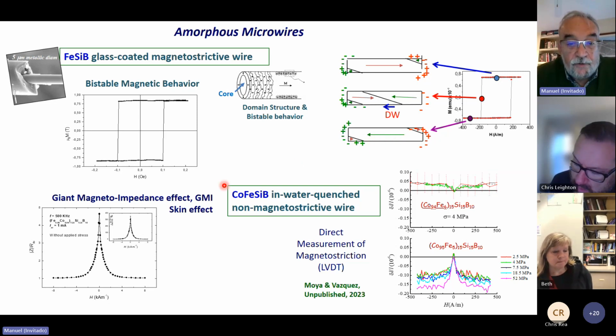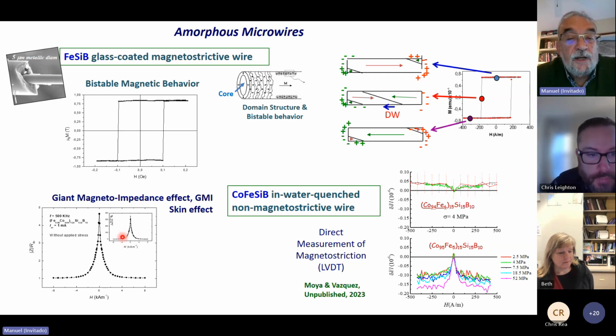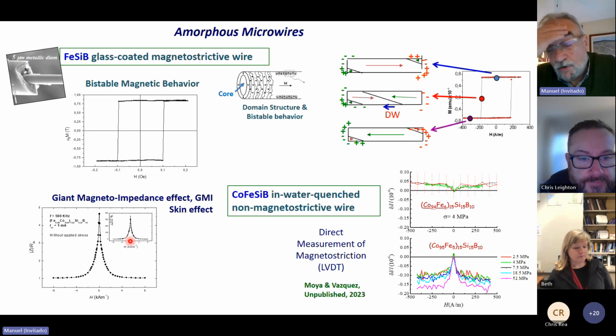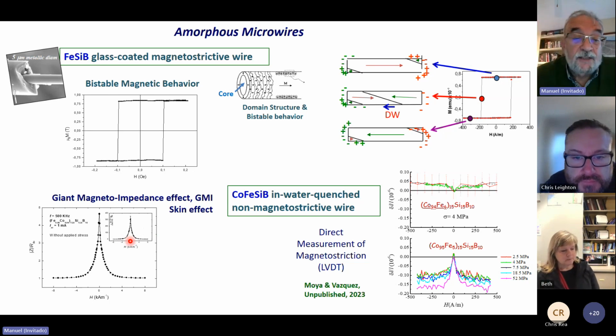In the case of cobalt iron based microwires, they are not magnetostrictive, and they are characterized by the giant magnetoimpedance effect, which is a classical effect based on the skin effect, by which the impedance of the amorphous wire drops very drastically when the microwire is put in the presence of a static magnetic field, or when we apply mechanical stress on the wire.